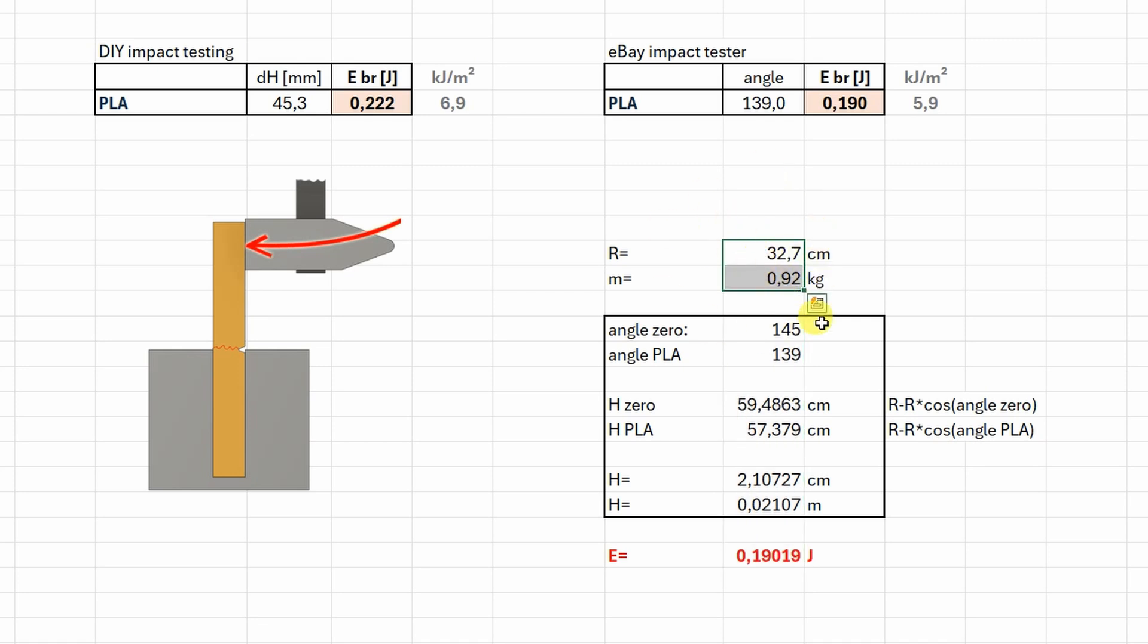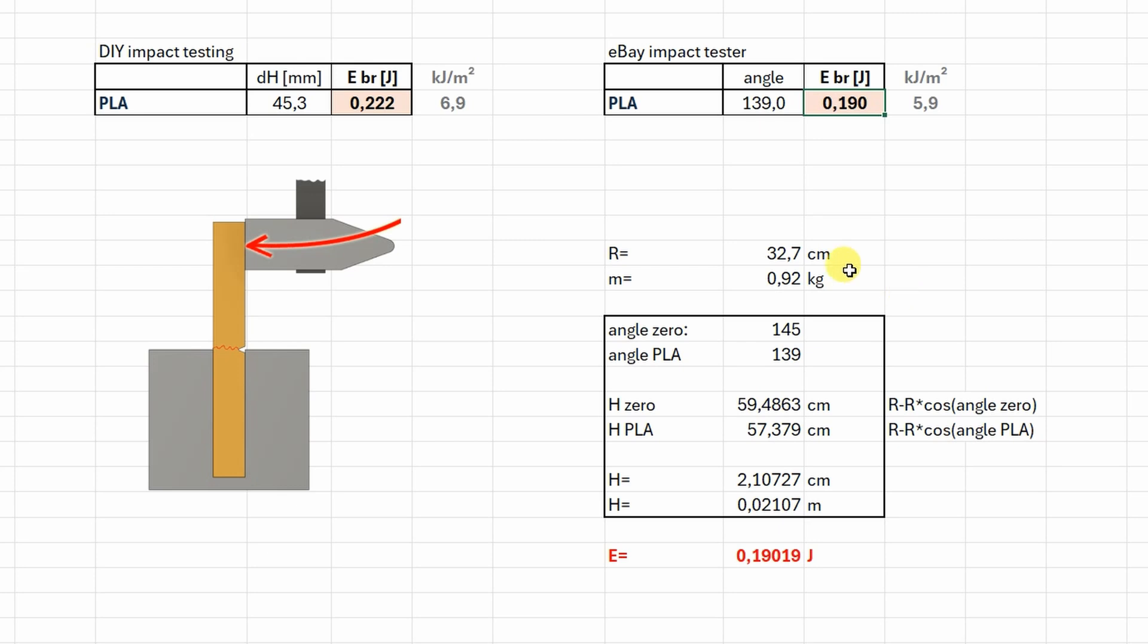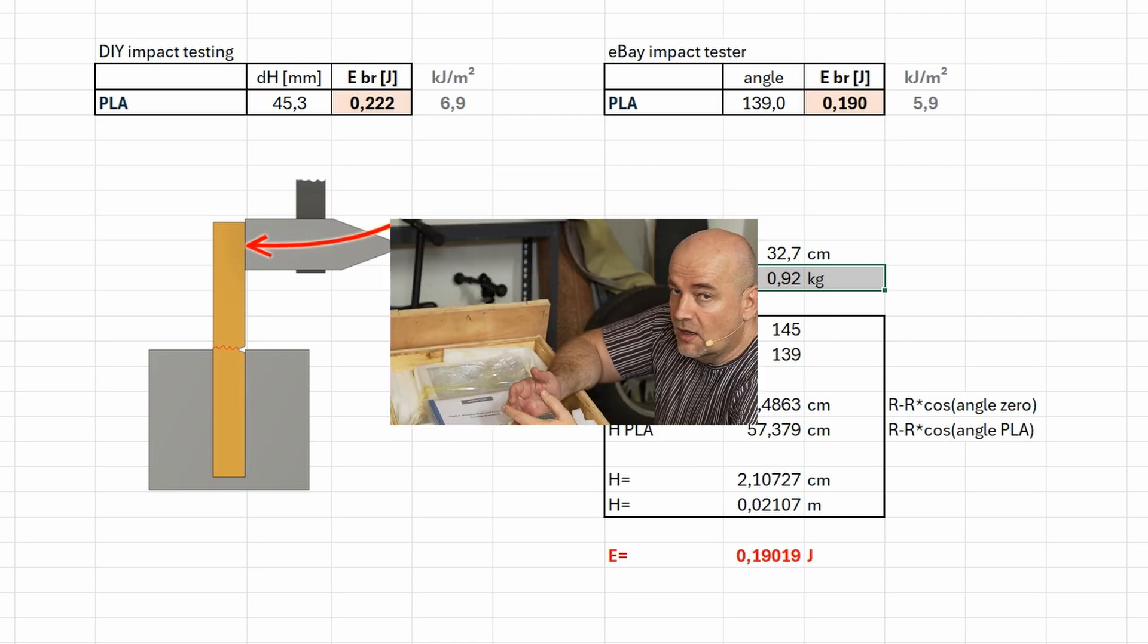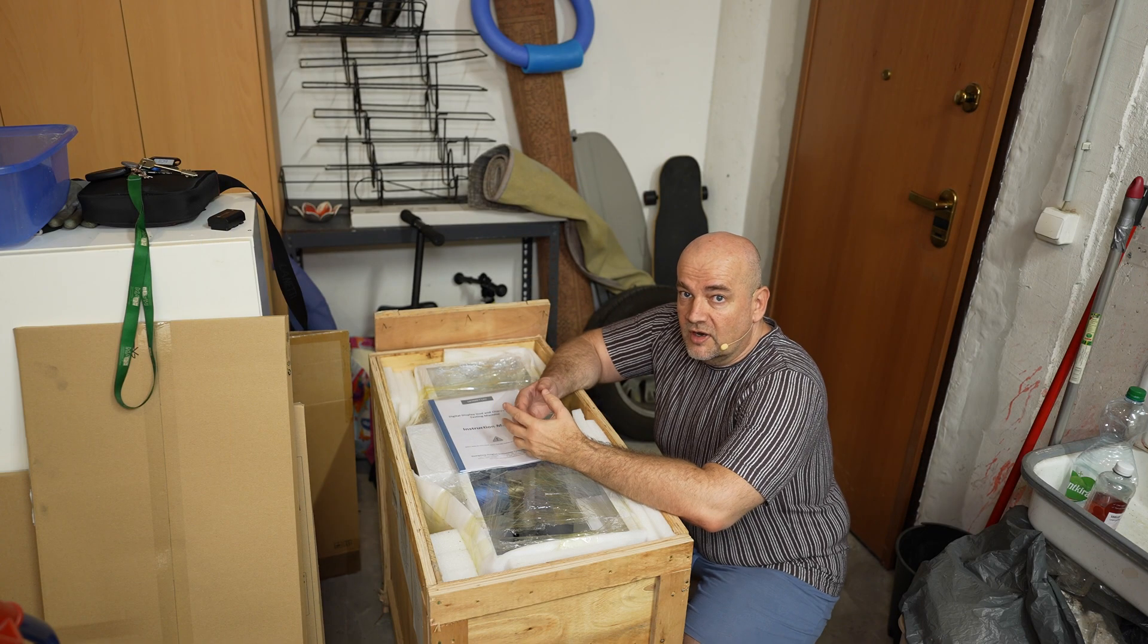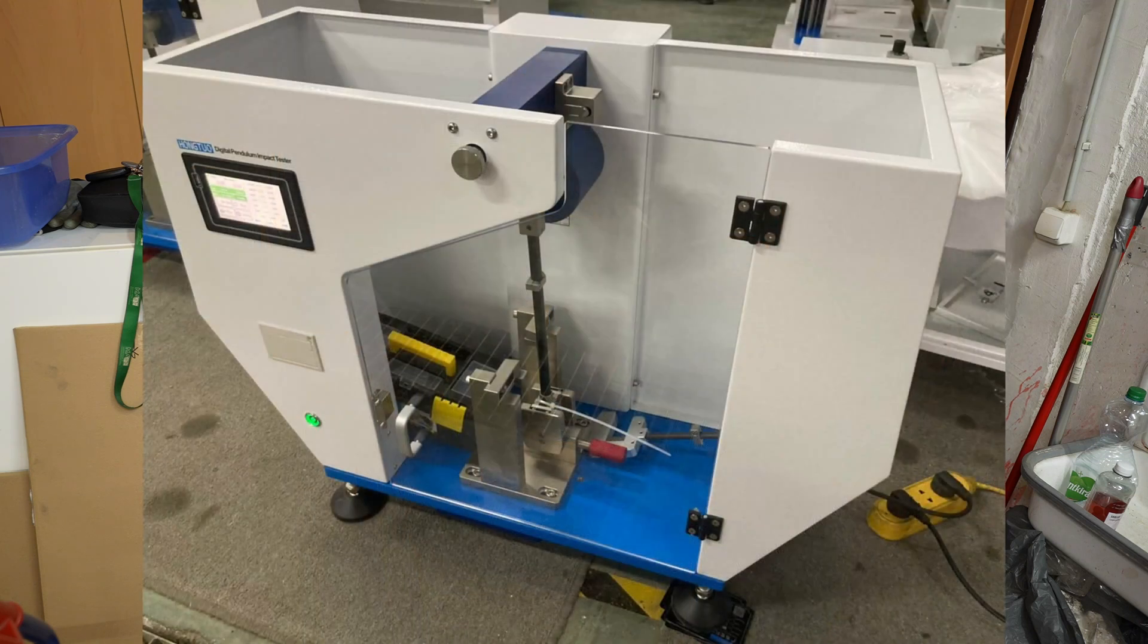I will use my newly calculated data to evaluate the numbers. With my DIY impact tester I measured 0.22 joules breaking energy. With the eBay impact tester I measured 0.19. Here you can see the calculation. But I'm not 100% sure about this data. Actually this data may be even equal, but definitely I have to use lighter weights because this is too much for the printed materials. From the reason I explained earlier, I was quite sure I was scammed. In the meantime I ordered another one directly from the Hung Ta company.